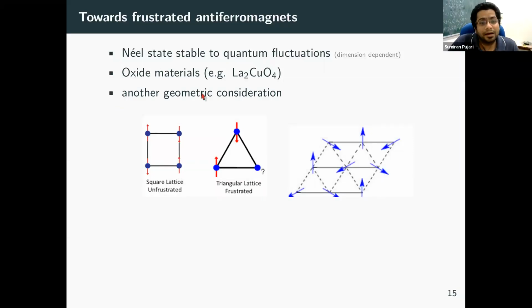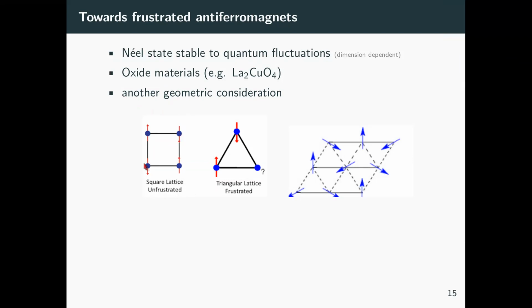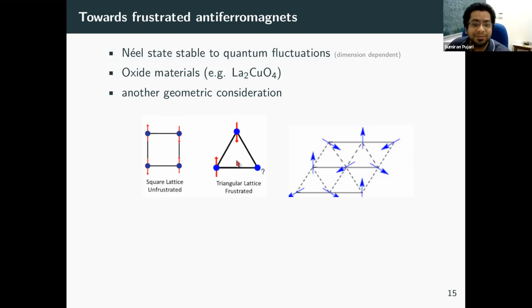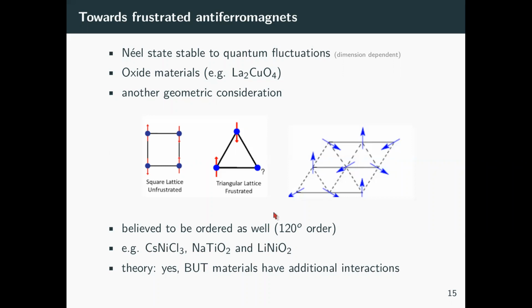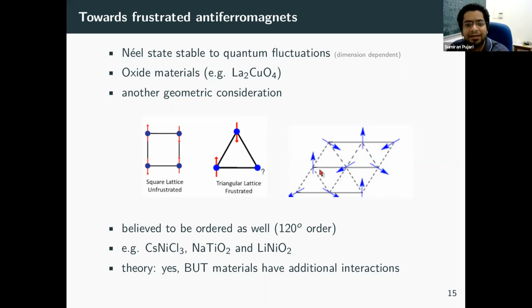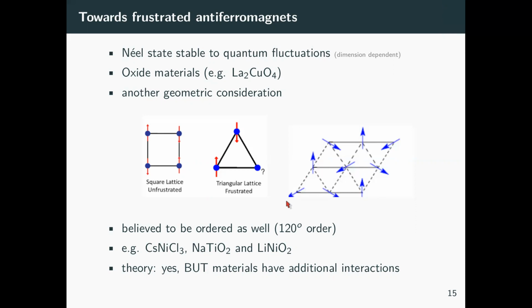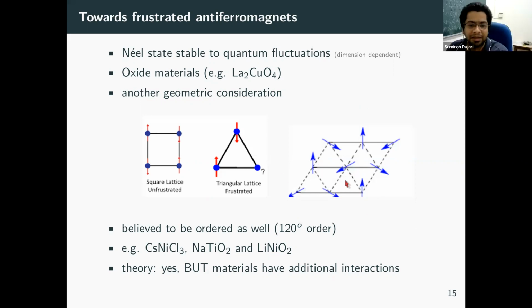However, there is another geometric consideration, which is this idea of frustration that I had mentioned in my outline slide. On the square lattice, the spins can perfectly anti-align with each other. But if you have a lattice with triangular motifs, then the spins have trouble deciding how they should arrange together. What is believed to be the case is that spins on a triangular antiferromagnet still arrange in this 120-degree pattern, which is shown on the right. You should see this as additional Bragg peaks in a neutron measurement, but this is what is theoretically believed to be the case. But real materials don't have just the nearest neighbor Heisenberg exchange interaction, they have additional interactions.